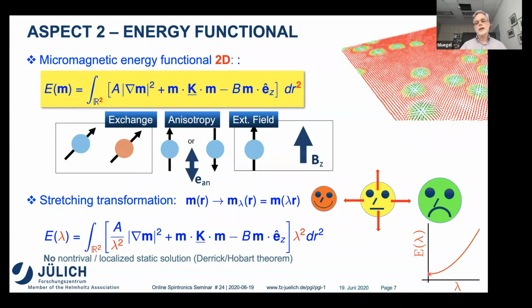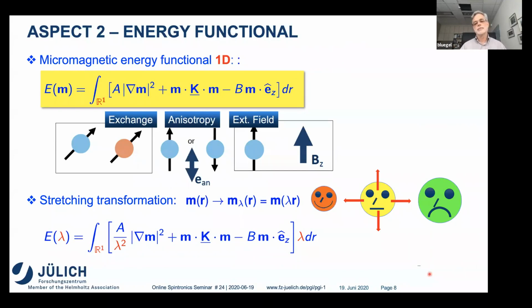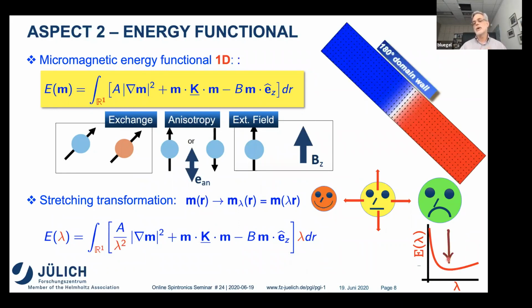And this is quite different from the one-dimensional state. If you have a one-dimensional particle, for example, then this r² here changes to r. This depends only on the stretching parameter lambda, but this is further depending on the stretching parameter 1 over lambda due to the first derivative square. Now you see your energy as function of this lambda has a minimum, and this minimum, you well know, is the domain wall, a typical domain wall. If you put a domain wall in your system, the domain wall may survive.